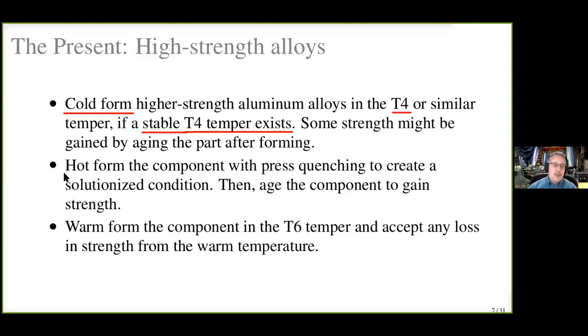So an alternative is to hot form. As we saw, the 7075 has very good ductility at hot temperatures. So a current process in development is something called press quenching. So this sheet of aluminum for sheet stamping, which is what I'm focusing on today, will be heated up to a little bit under 500 Celsius. It will then be stamped into cold dies. So the dies actually act to quench the material down while the part is formed. Then it must be immediately aged to get the T6 temper.